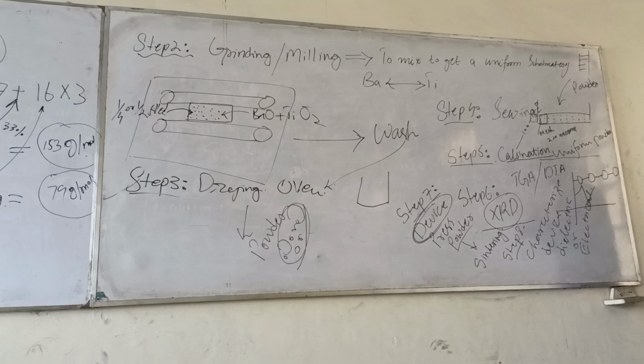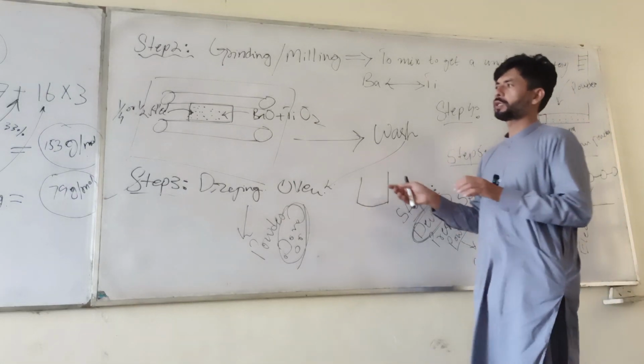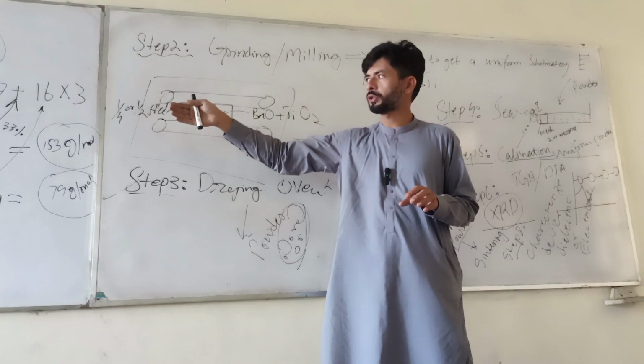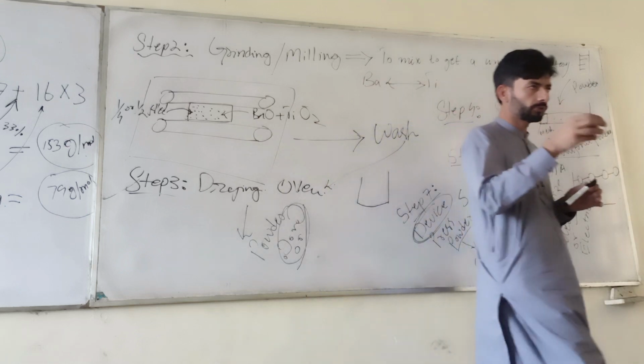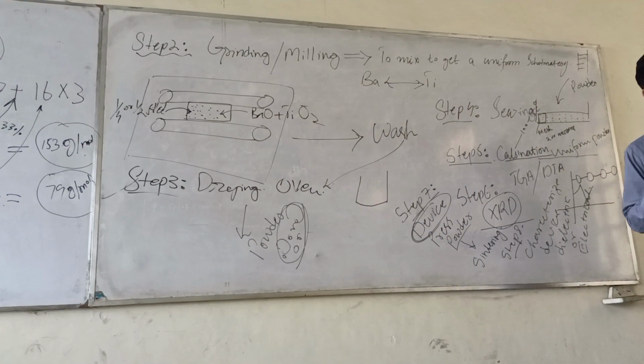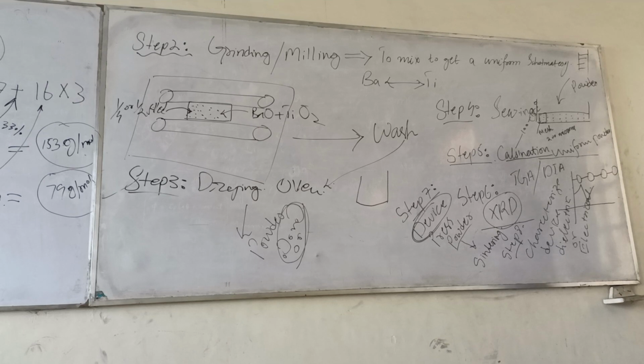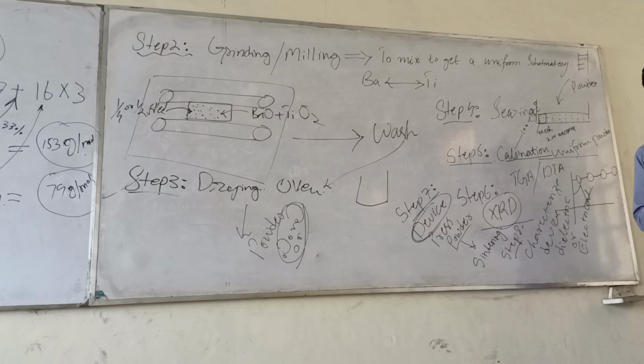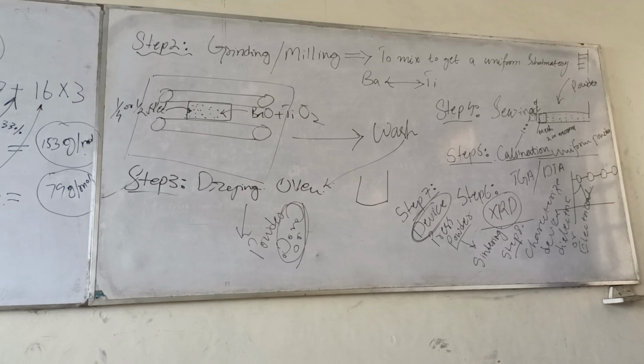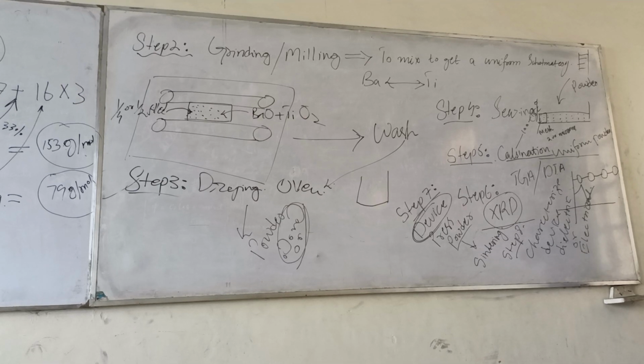So if your composition contains some electropositive and electronegative atoms, there is some probability that they can react or interact with it. So it is better to use a virgin alumina crucible instead of a porcelain-type glazed crucible. Okay. They are a little bit expensive, but if your research is very precious, then use this one. If it is not precious, then you can use the other. Yes.